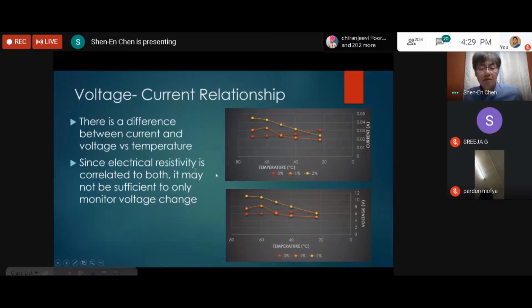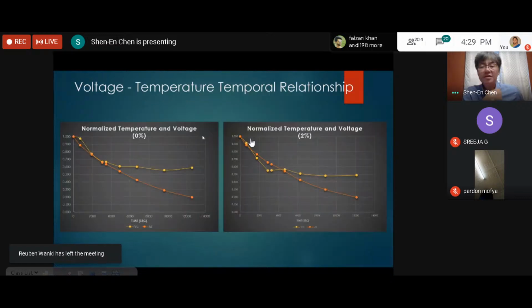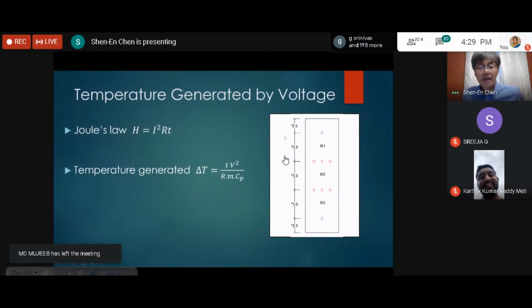Okay, so it becomes apparent to us that the technique needs to have both current and voltage measurements in order to accurately quantify the change in resistance. But that makes the technique a little too complicated. And so again, we're trying to develop a correlation between temperature change and the voltage measurements. And we were able to use both Joule's law and the temperature change to develop a correlation between the two.